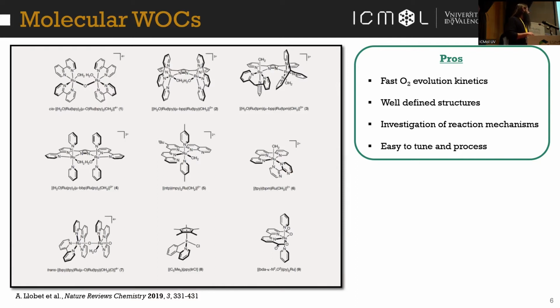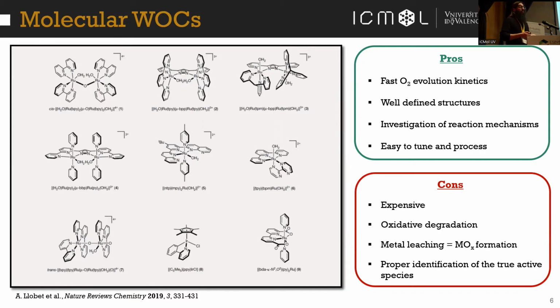And they are very, of course, easy to tune and process. But they have many drawbacks because the most active catalysts in these conditions are made out of ruthenium, so it's an expensive metal. And because they have organic ligands, they don't survive very long under oxidative conditions. And this produces metal leaching into the system, so you are applying oxidative potential. When you have metal ions in solution, you will create an oxide layer on the electrode. And basically, this will preclude the identification of the true catalyst, because this metal oxide will also be pretty active